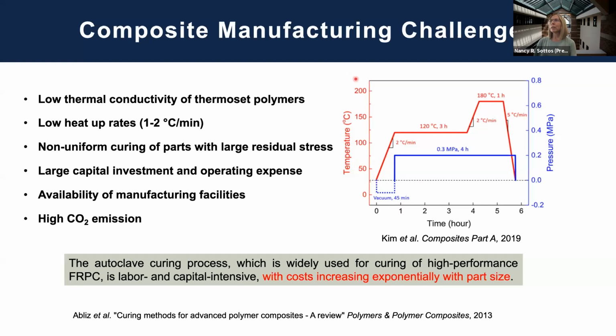High temperatures held for those long times, usually 2 dwells. And the heating rates are low. Sometimes the curing can be non-uniform. You induce residual stresses. And those large molds and autoclaves I showed on the previous slide require large capital investment and operating expenses. And you have to have these manufacturing facilities available. And of course, there's a lot of energy in, and that leads to CO2 emission.